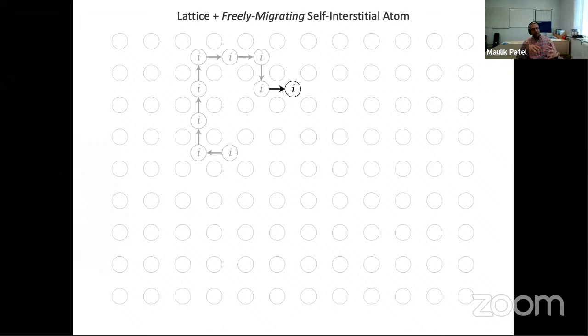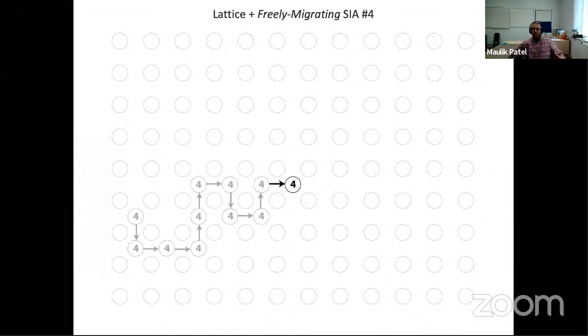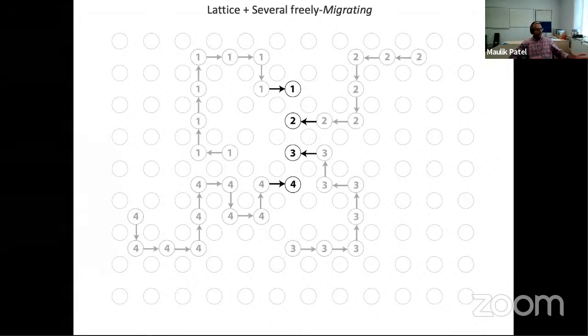And when you have more neutrons coming in, they will cause more of these primary knock-on atoms, which then move. So the neutron imparts its energy to one of these atoms in the target. The target atom moves, which is a recoil, and then they will further cause more displacements. And hence you create more and more interstitials as radiation comes in and hits the materials, so to speak.